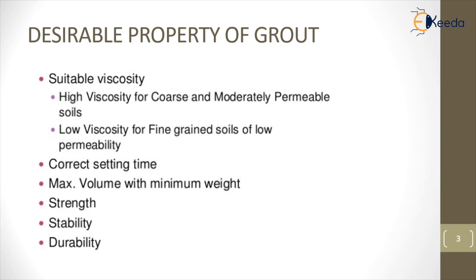Let's see the desirable properties of the grout. It should have a suitable viscosity. A grout having high viscosity can be used only for coarse and moderately permeable soil, whereas the grout having low viscosity is used for fine grain soil of low permeability, so that it is easy for that low viscous grout to reach all the voids.